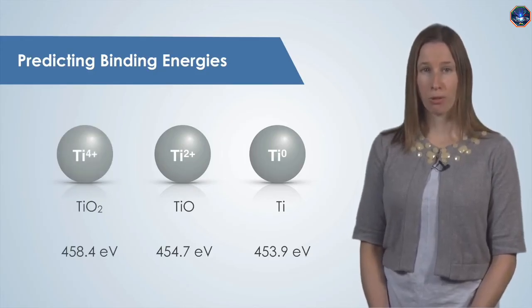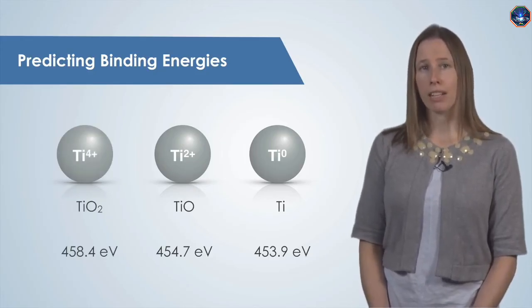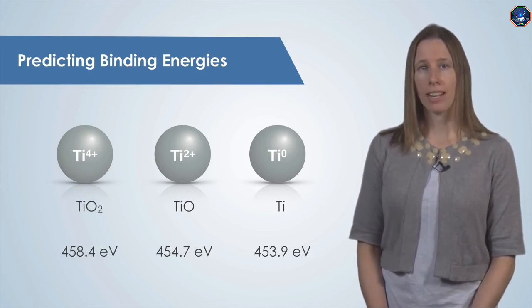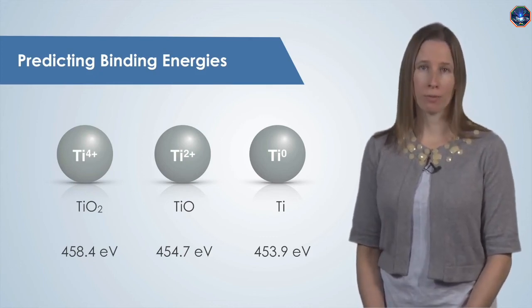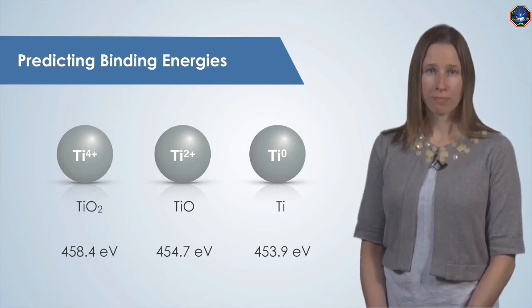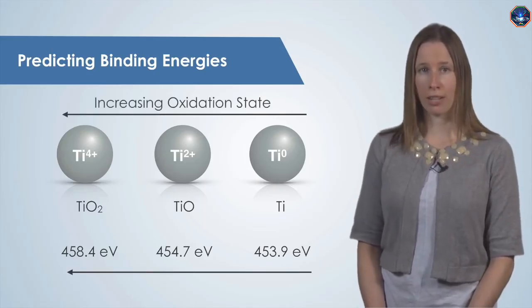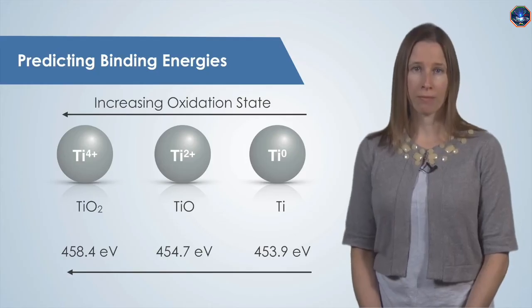Finally, titanium dioxide, or TiO2, contains titanium in the 4-plus oxidation state, and the binding energy shifts to an even higher value. In general, as the oxidation state for an element increases, so will the binding energy.